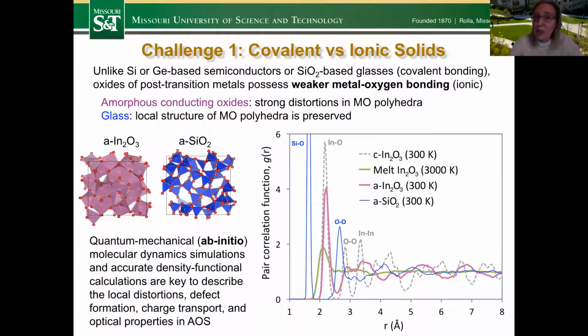So there are some challenges, and here I start from the very first one, to put a difference between, again, the silicon semiconductors or germanium-based semiconductors and also glasses. In all these materials, we have covalent bonding. We know exactly the distances, and this is a strong bonding in both silica and silicon. But unlike those materials, in oxides of post-transition metals we are dealing with ionic, much, much weaker metal-oxygen bonding.